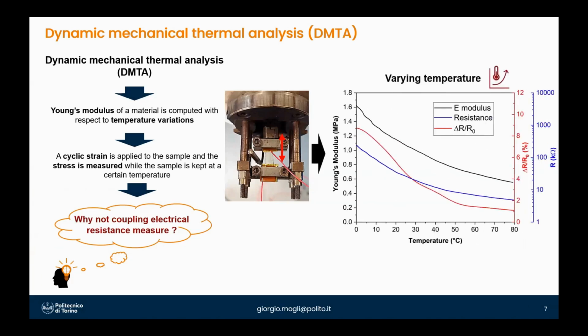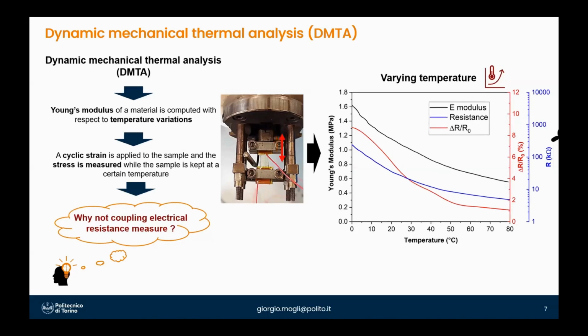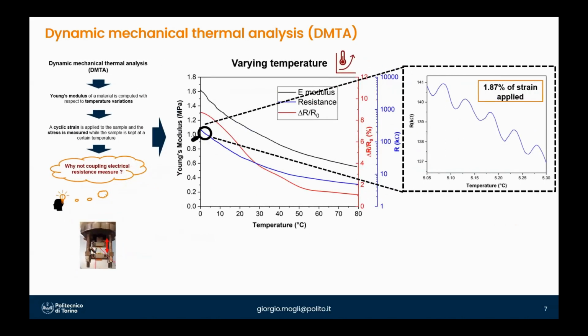And we found this graph, in which we can see that the Young's modulus, the black line, obviously decreased when the temperature increased because the mobility of the polymeric chains increased, and the resistance, which is the blue line, as we can see from this zoom, is responsive to the external cyclic strain applied. This resistance decreased while temperature increased because the ionic mobility is enhanced.